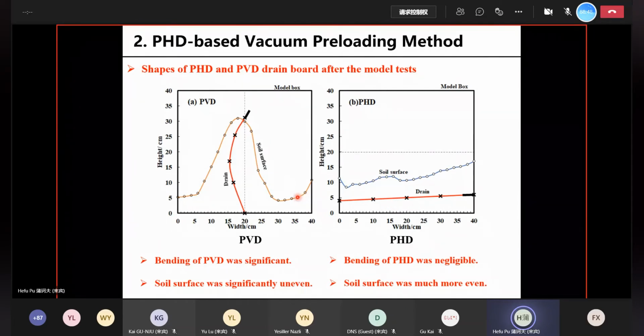And the yellow curve is the soil surface after the treatment. We can see that the soil surface for the PVD was significantly uneven. We have a very uneven surface, which means the treatment will be also uneven. On the right-hand side, the soil surface was much more even relative to the case on the left.